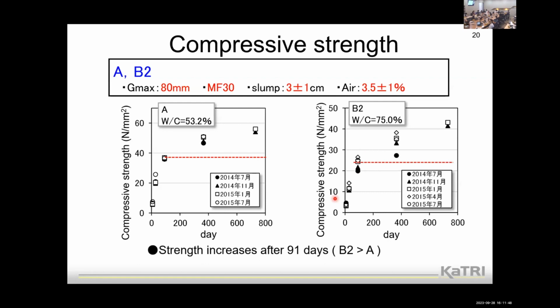So we often estimate compressive strength at 91 days, and then, as you know, from 91 days compressive strength increases for 2 years and more. And when the water-cement ratio is high, the increase is greater. So for B2, where W/C is 75%, the compressive strength from 91 days to almost 2 years doubles.